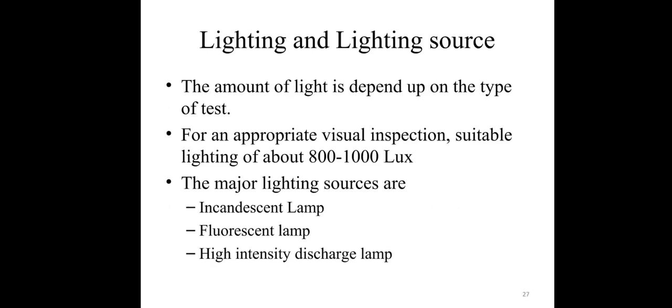Light and light source. The amount of light depends upon the type of test. For an appropriate visual inspection, suitable lighting of about 800 to 1000 lux is needed. The major lighting sources are incandescent lamp, fluorescent lamp, and high intensity discharge lamp.